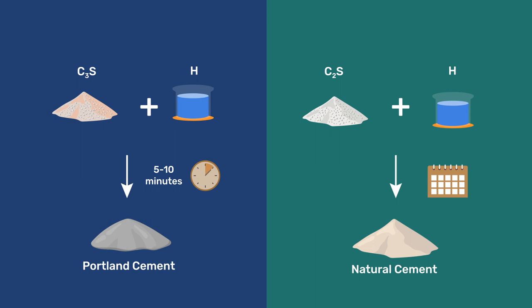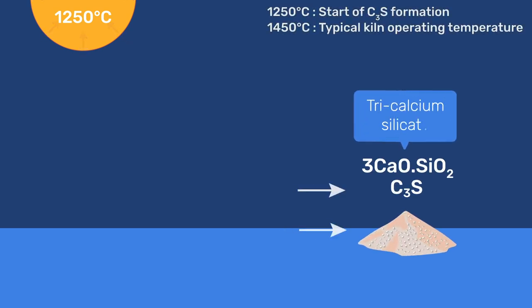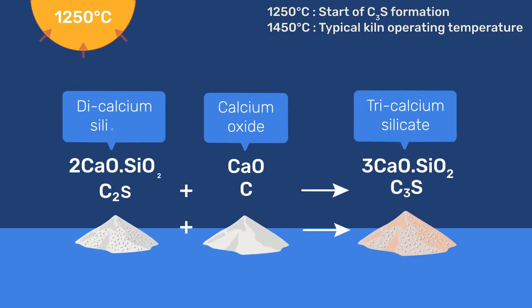The much faster hydration of C3S over C2S is largely responsible for Portland cement having eclipsed natural cement. The fact that C3S only forms at temperatures above 1250 degrees Celsius explains that clinkering is necessary to produce it.